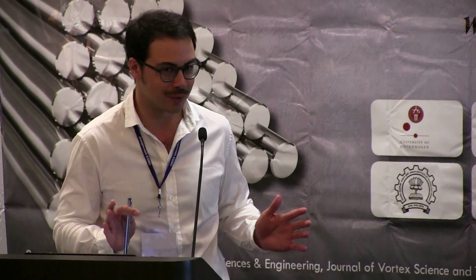And now the poor wire, we see it didn't show a real SMA effect. When it was heated up, it got longer, so it was really destroyed. So you see, it's not the way it should react as an SMA device. And so we can say that variations of production process parameters cannot be compensated by a subsequent SMA training